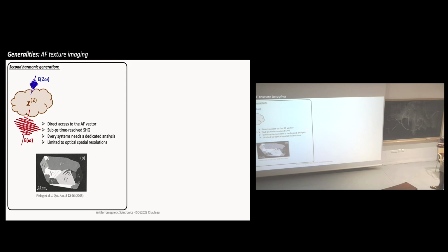I like to say that several times because it's worth the time. And on top of this, most of the time we do this with femtosecond lasers. So for free, or almost for free, we can have these time-resolved capabilities on these systems. But some drawbacks are, of course, that every system needs dedicated analysis. You cannot take one analysis for granted. If you change the symmetry, change system, then you have to go back to the group theory and symmetry analysis. And it's definitely limited by optical resolution. So that's one of the techniques.